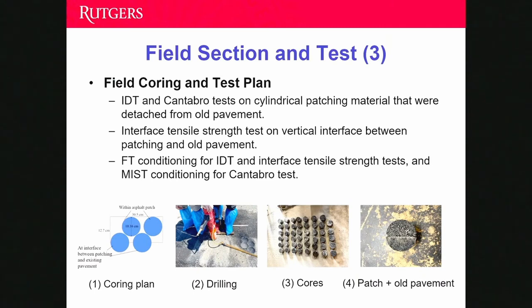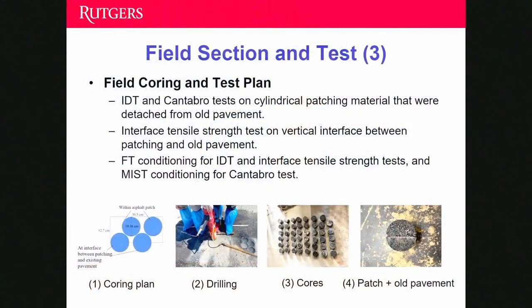And even with the factory compaction, we still observed some damage during the drilling. So almost all of the patching material detached from the old pavement at the horizontal interface. So we decided to do the IDT and the countable test on those detached patching material because they are pure patching material. And then we did the interface tensile strength on the patching material with the vertical interface.